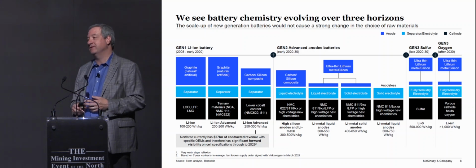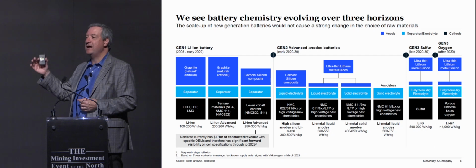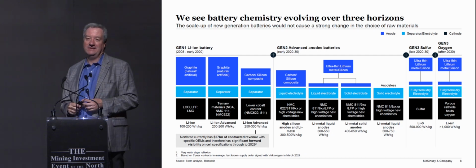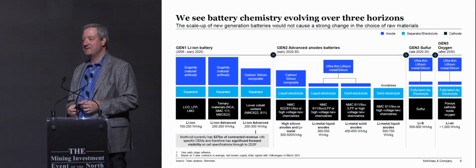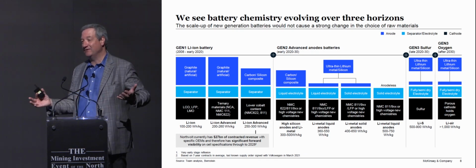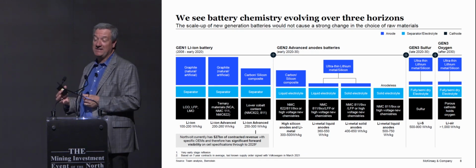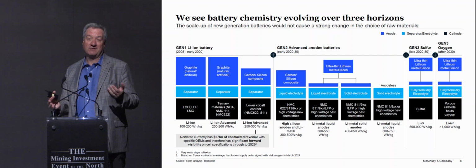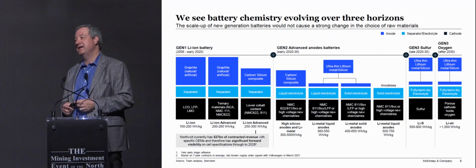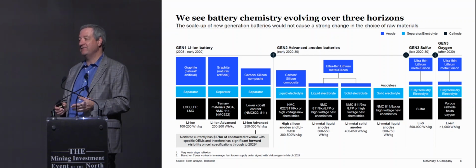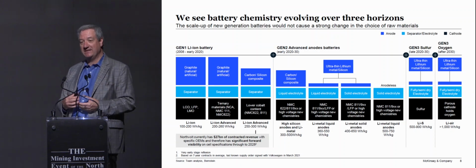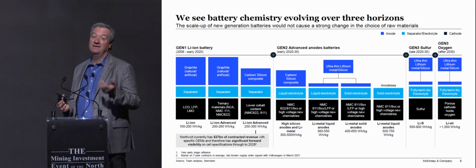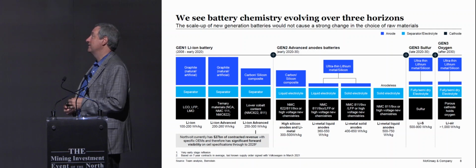Now, going forward, we spent a lot of time over the last 10 years tweaking the cathode material. So you've seen a move towards higher and higher nickel, and now we're at, you know, the GM Ultium batteries over 90% nickel. There's almost so much nickel you can put into it. We are seeing moves towards a high manganese battery. A company in China called S-Volt has a 25% manganese, 75% nickel battery. So they've taken some of the nickel out, and they still get good density.